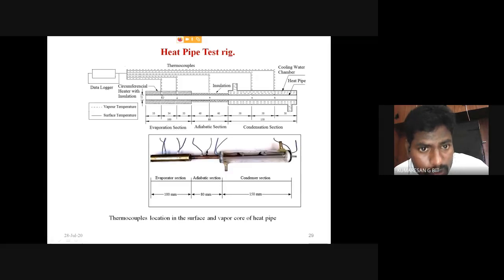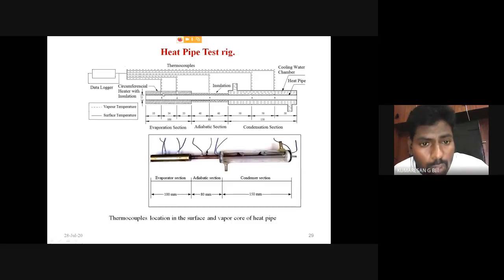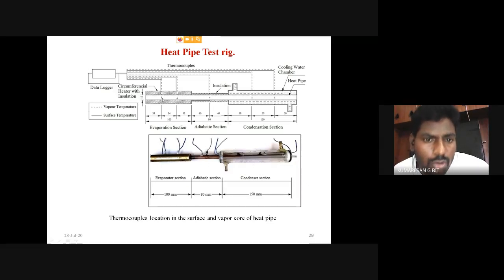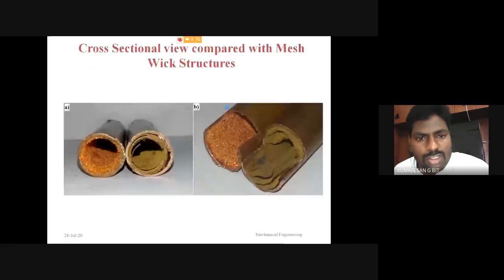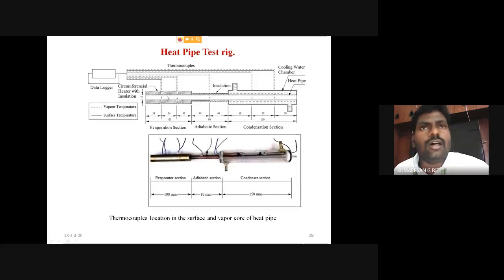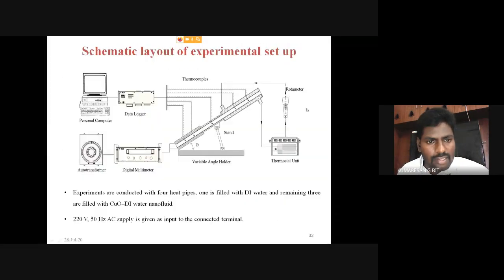the surface and the vapor core. So you see here, two thermocouples are attached to this section. One thermocouple, mentioned by the dotted line, is fixed in the center core area of the heat pipe. Another one is fixed over the surface, which is used to measure the surface temperature of the heat pipe. While calculating the heat transfer coefficient, these two thermocouple readings are taken into account. The difference between the surface and vapor temperature of the evaporator section, and of the condenser section, are used to calculate the heat transfer coefficient values.